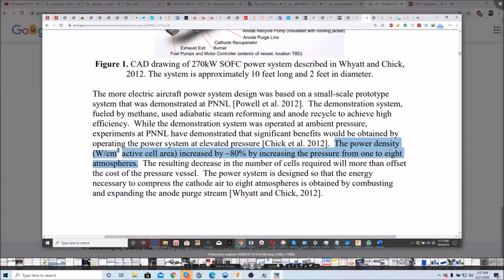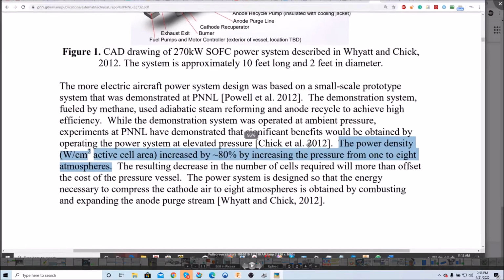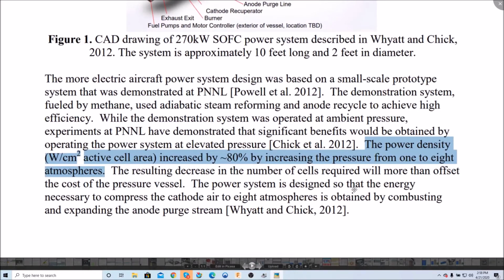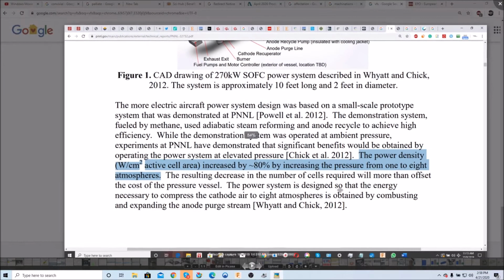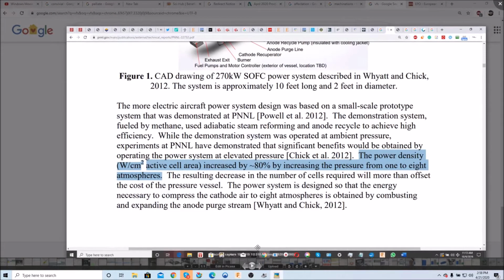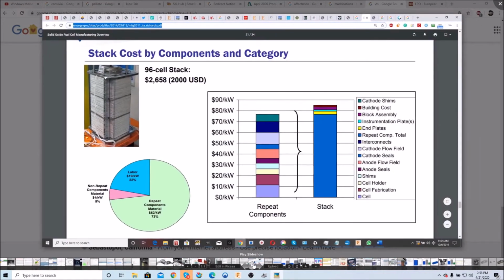So fuel cells increase in power output at higher pressures. That makes sense. New fuel cells are being designed to run at higher pressures. That's one potential issue that needs to be addressed with the ammonia reaction, is that for ammonia decomposition, you want to be at the lowest pressure possible. So the rate of reaction decreases at higher pressure. The highest conversion rates are found at very low pressures.